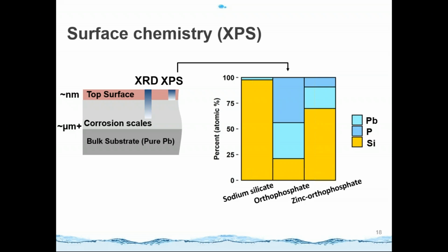As the figures on the right show, the percentage of silicon, phosphorus, and lead. In the sodium silicate treated system, we did observe the silicon-rich coating. The percentage of silicon is more than 95%. But in the orthophosphate or the zinc orthophosphate system, the percentage of silicon is relatively lower compared with the sodium silicate treated system.